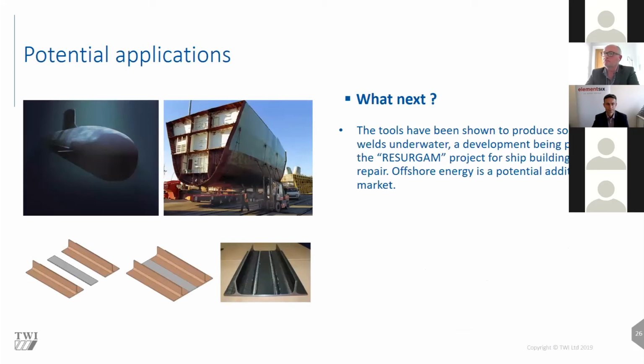So in terms of potential applications, one of the things that we've been looking at is what we can do in terms of maritime and shipbuilding. One of the things we've looked at is that the tools work perfectly well underwater. We can make a weld underwater with no real problems. The very low amount of distortion that we see from the tools is very useful if you're building ships using modular construction. When you bring those parts together, you've got a pretty good chance that they will all fit, which is quite important when you're doing that kind of structure.